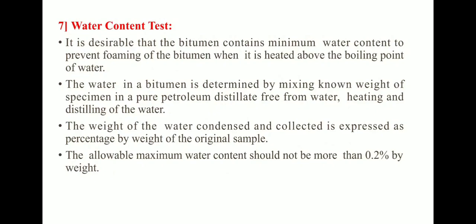The next test is the water content test. It is desirable that bitumen contains minimum water content to prevent foaming when heated above the boiling point of water. The water in bitumen is determined by mixing a known weight of the specimen in pure petroleum distillate free from water, then heating and distilling off the water. The weight of water condensed and collected is expressed as a percentage by weight of the original sample. The allowable maximum water content should not exceed 0.2 percent by weight.